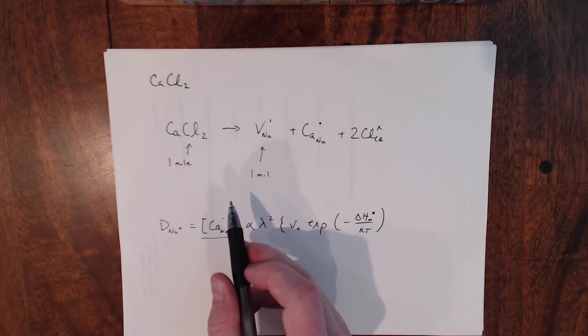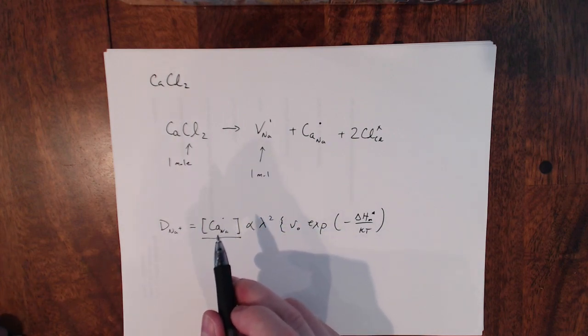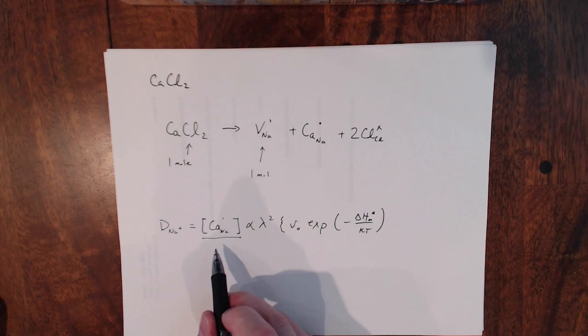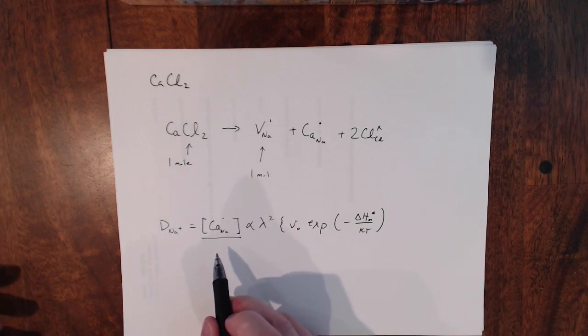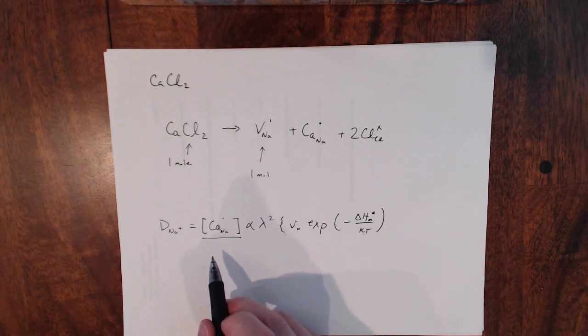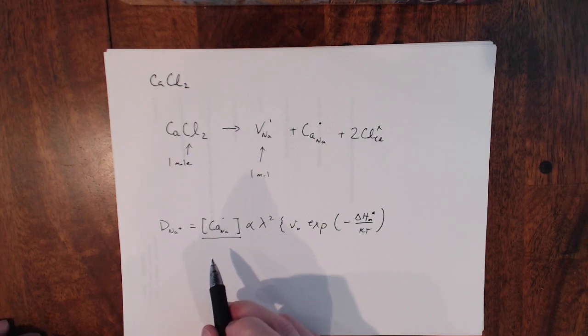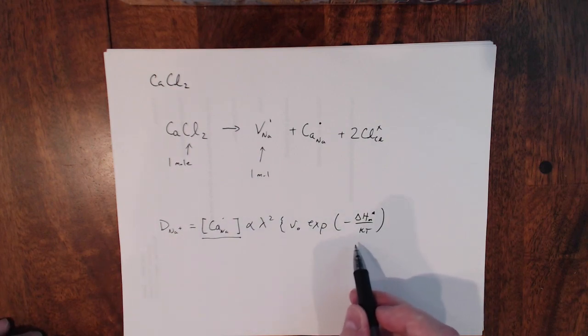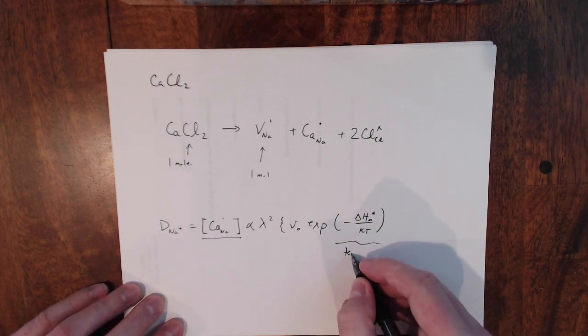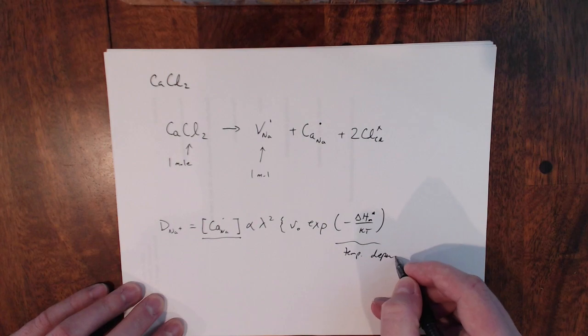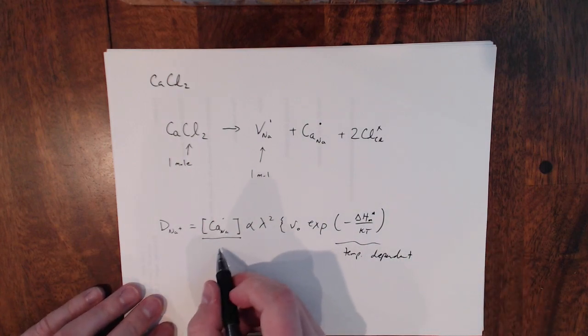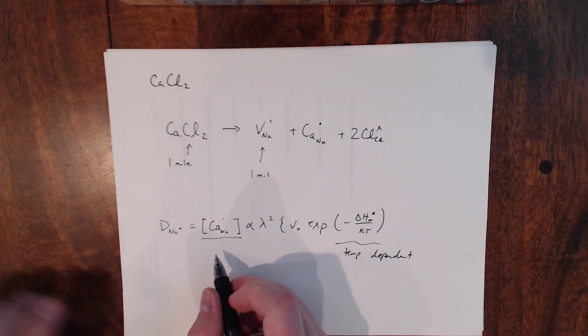And so when we think about if it's governed by this extrinsic concentration of impurities, then instead of being governed by temperature, like the other reaction, this is governed by the concentration of dopants, right? And so that's not something we're adjusting during this experiment. So we'd expect this to be consistent with temperature. And so the only factor of temperature then is the migration term that we've seen here. So this is the temperature dependent part. And then the concentration is fixed for a level of doping, right?